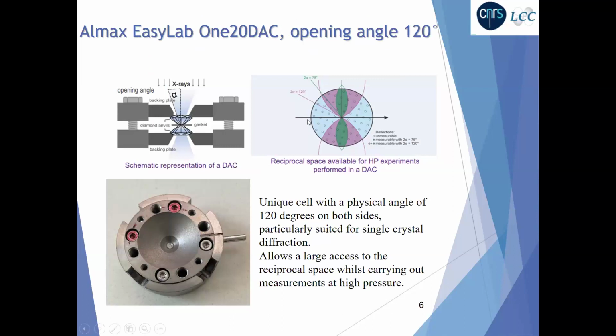You can see on this nice diagram in green the portion of the reciprocal space available with the small angle DAC we had before, 75 degrees. And in pink, you can see what we have now with the new DAC, a 120 degree opening angle.